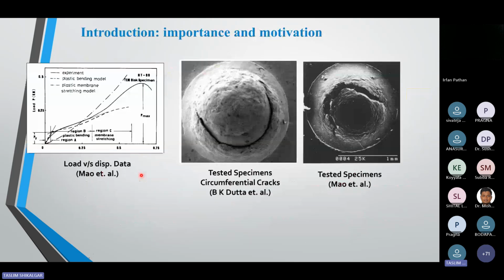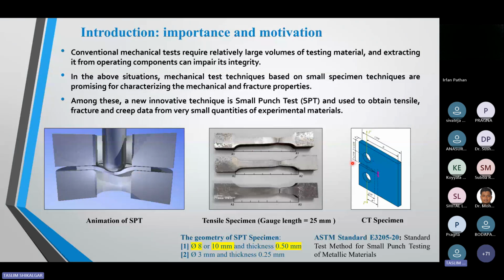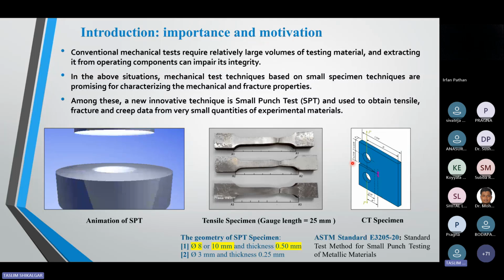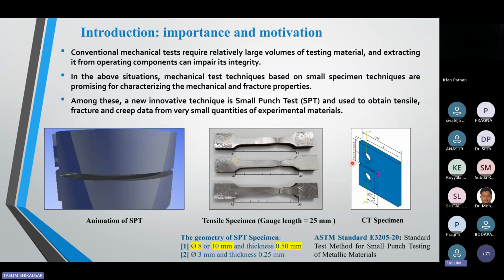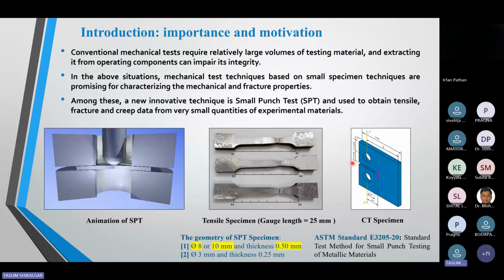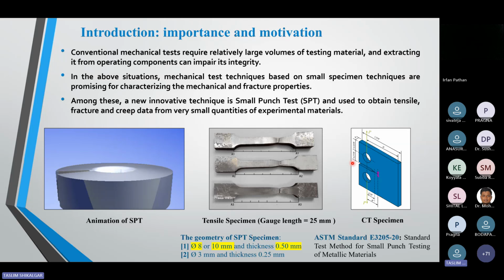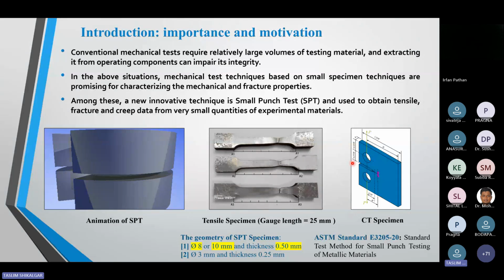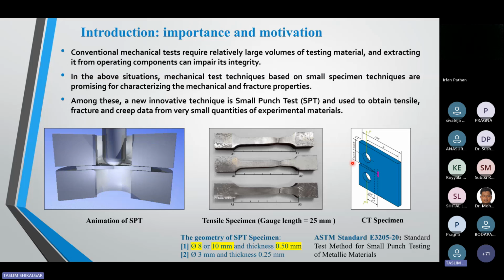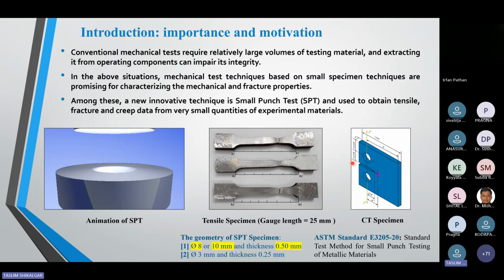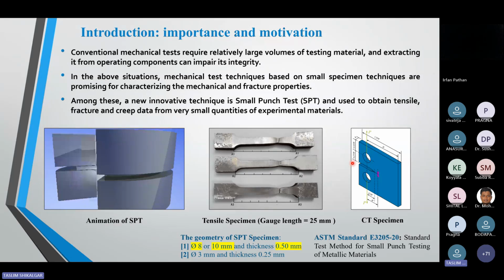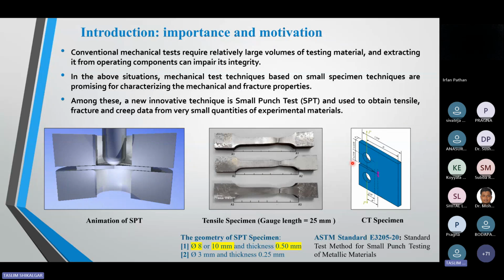If you see this type of specimens, like tensile specimens as well as CT specimens, there is no space available to keep these specimens. You cannot extract these specimens from the nuclear pressure vessel to find out the exact ongoing property. So sometimes people fabricate these type of specimens and keep them inside the nuclear reactor, and every year or every 2 years they take these specimens out and test them, so they find out the ongoing properties of the nuclear reactor.